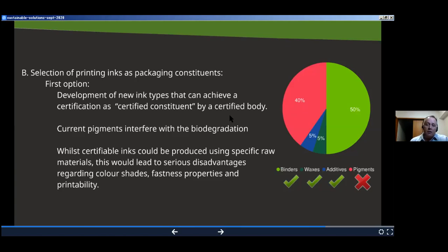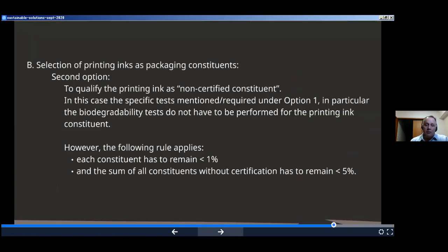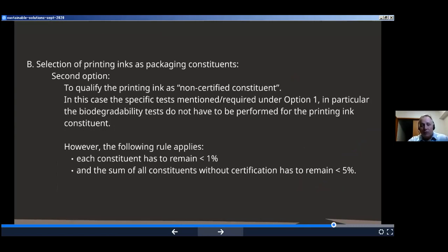So the other option is to use inks which are not certified as biodegradable, but we can use them within a certain limit amount. So if every single ink represents less than 1% of the weight of the packaging, and the total amount of the inks is less than 5% of the weight of the packaging, it's considered that this will not affect the biodegrading process. And if the substrate is biodegradable, the final packaging will most probably be biodegradable by itself.